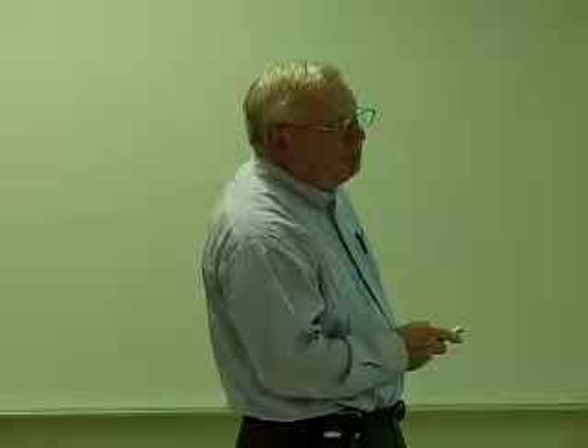Here's an example, a couple of examples of tin whiskers. You can see here we have some leads. You can see the whiskers have grown and potentially can short between leads. Here's a material where you can see a lot of tin whisker growth has occurred. And one of the things that's really kind of scary about this is I've heard people from Jet Propulsion Labs say that tin whiskers can grow many years after the component was made and assembled.